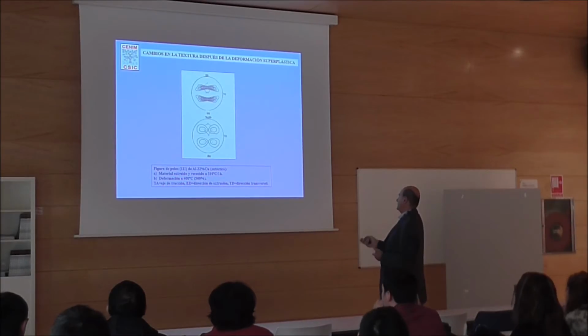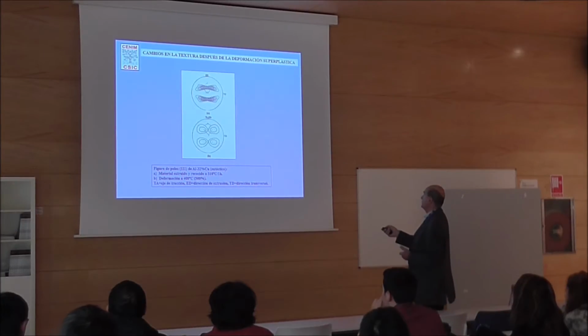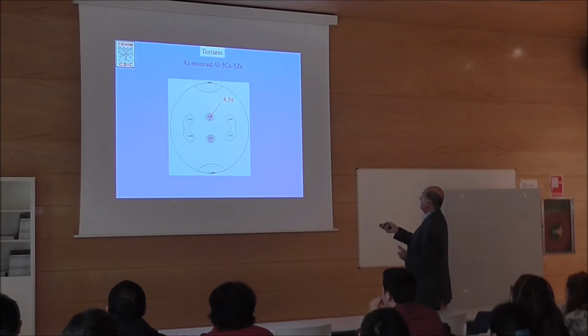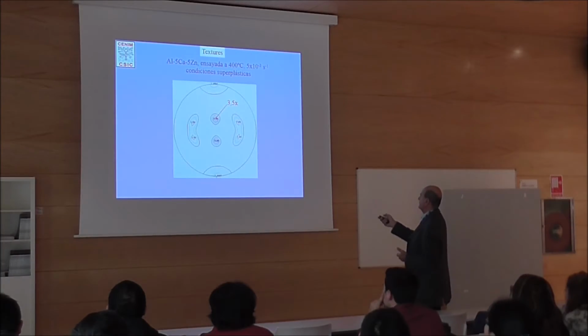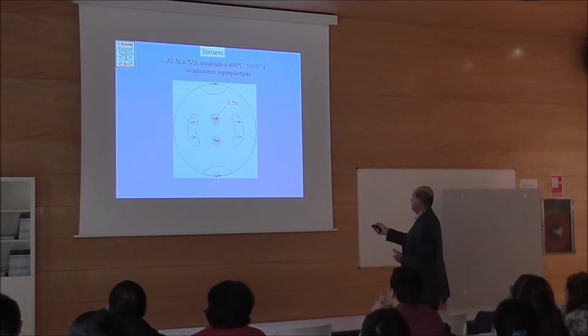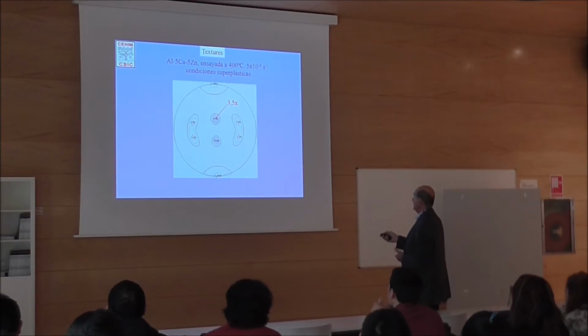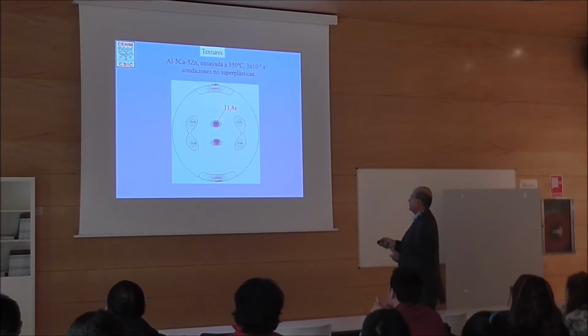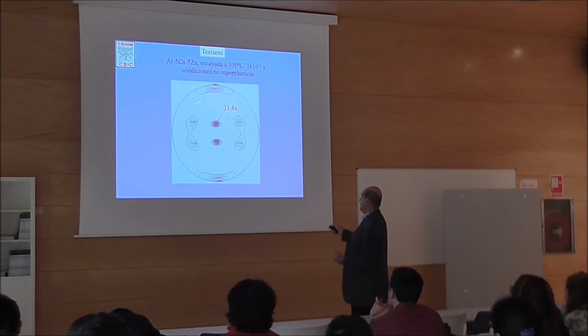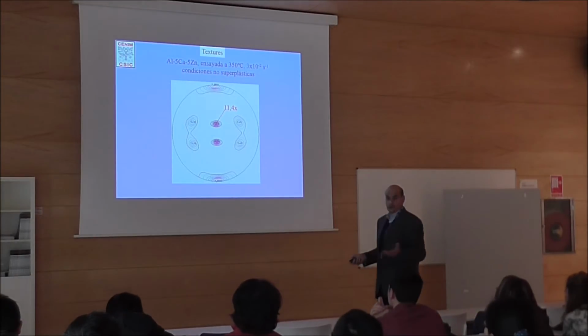Texture disappearing, this is an example. This is as received, with its intensity of the texture, and then after deformation, probably 200% deformation, you have a reduced intensity. If you measure that in the slip region, you have reinforcement of the texture component.